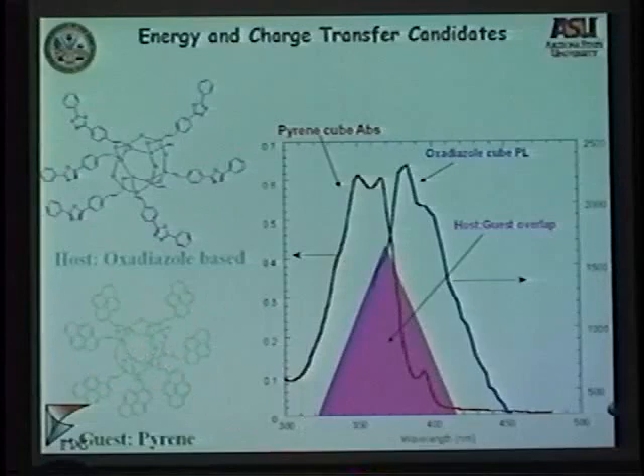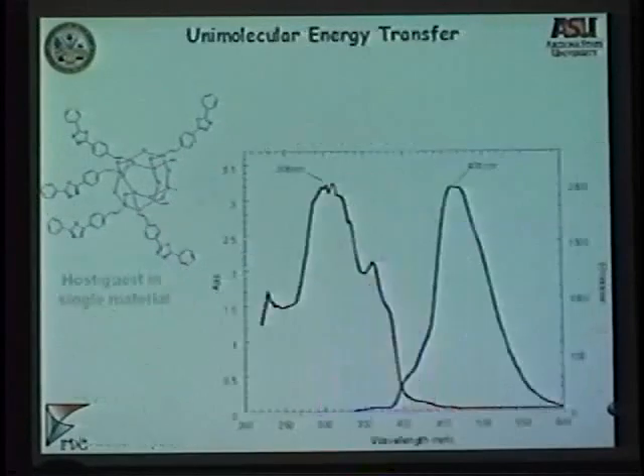So instead of mixing two materials, we take this material and put it on the same cube, and this is what we did. So this is the simplest sensor basically, or light emitter on the nanoscale. You excite the PBD or the oxadiazole, and you will see emission directly from the pyrene. The single molecule pyrene on a cube, you see emission from it.